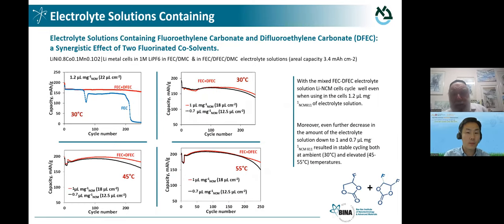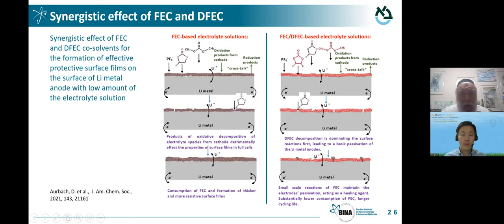I just want to emphasize in this slide where I demonstrate that when we have both FEC and DFEC, we can extend cycle life because here they work synergistically. DFEC reacts first to form the surface films, and then FEC is a healer. And whenever there are any cracks, the FEC, which is remaining in solution, can help to heal whenever we have any cracks or discontinuity of the SEI. So we have the following mechanism. First of all, formation of surface films thanks to the reaction with DFEC, which is the more reactive. And then we have FEC in solution that whenever we have cracks, reacts and heals the crack. And in such a way, we can demonstrate a prolonged cycle life of lithium anodes.